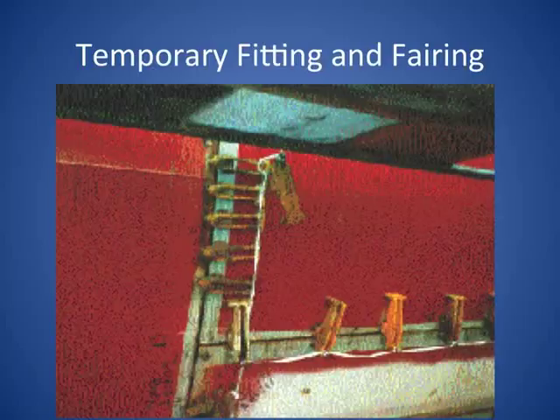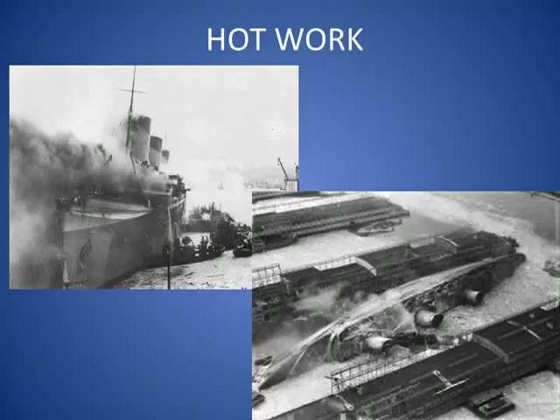The problem is, anytime you do any temporary welds, you have to break those welds off. Often when you break those welds off, you damage the underlying plate. So you're into the cost of welding these attachments and then also making the repairs after they're done. So that's sort of my aim, is how to avoid that. A couple other things you like to avoid: if you're using adhesives, you're not doing hot work. You don't have to gas free. You can effect temporary repairs, sometimes fairly quickly at sea. And you can avoid galvanic corrosion because it's somewhat insulated, or at least galvanically insulated.